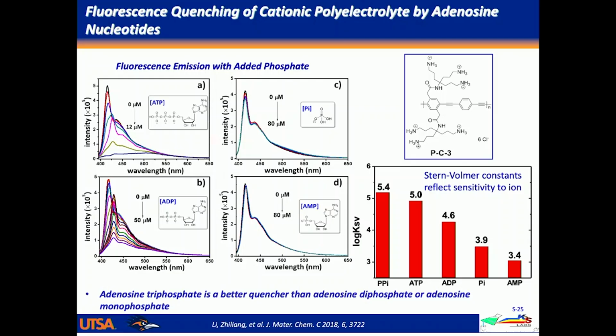and in particular, what I'm showing here is this branched polyelectrolyte. And it turns out, not surprisingly, that it interacts most strongly with the adenosine triphosphate. It takes only about 10 micromolar to induce very significant quenching of the fluorescence. The diphosphate analog, ADP, we have to add more of it, and it doesn't quench quite as efficiently. By contrast, the monophosphate alone really doesn't give any quenching at all. So it takes at least 2 phosphates, and 3 is better than 2.